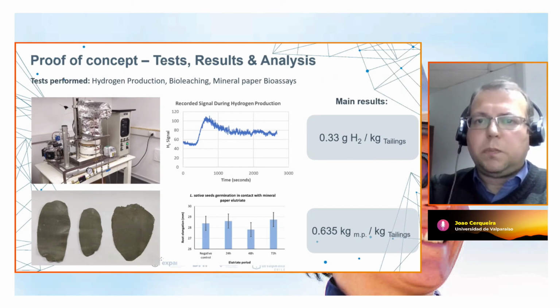The first picture corresponds to the machine that had to be constructed specifically for this work, which allowed the production of hydrogen from tailings. In the middle, we can observe a graph obtained during one of the hydrogen production tests, from which a sample was taken for 18 minutes and analyzed by an independent laboratory. The results indicated that for each kilogram of tailings, a quantity of 0.33 grams of hydrogen was produced.